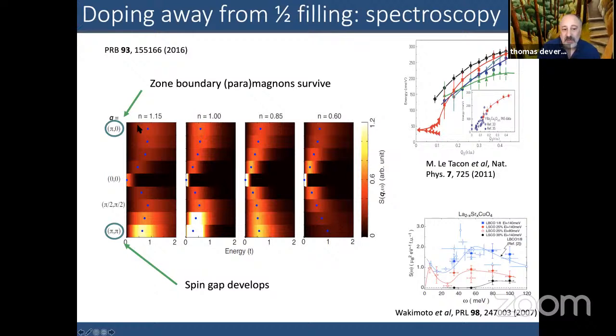If you look though at the zone boundary, say at (pi, 0), if you dope with holes, you see that this blue dot, which is just plotting the maximum of the spectra, doesn't really move very much with hole doping out to 60%. And there's a slight intensity decrease, but it's not as prominent as one sees out here, out at (pi, pi). And importantly, a counter is when you dope with electrons, in fact, this blue dot is at larger energies than this blue dot. So as if magnetism increases when one dopes by 15% electron doping. And so these two things have been really